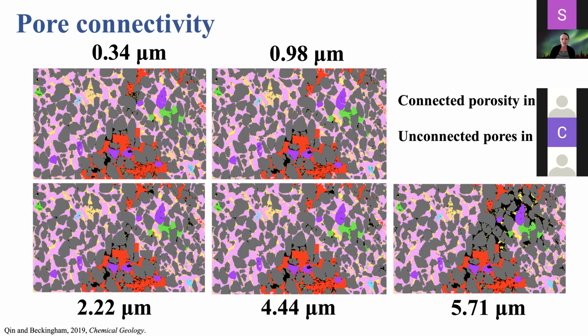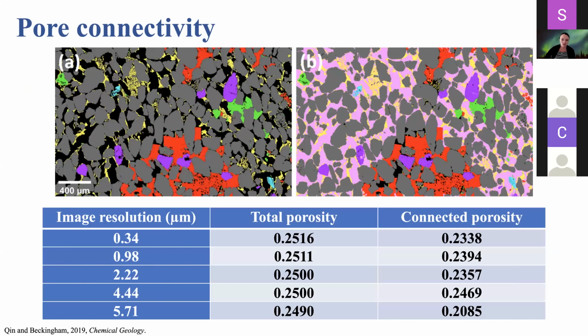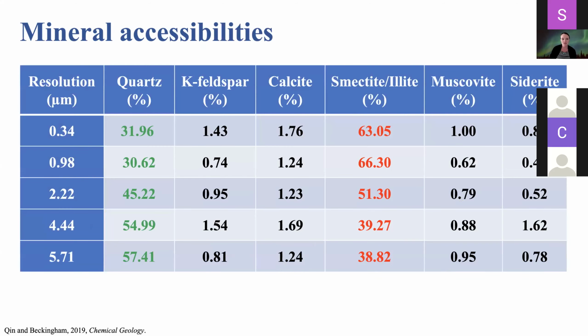So you can see a lot of the pore space is connected, but we do have some unconnected porosity in the sample. And then we can quantify that, where we saw some variation with image resolution, but no overall trend in terms of increasing or necessarily decreasing with resolution. We can then quantify what the accessibility of these different mineral phases are, where that is telling you the accessibility to where the fluid's going to flow.